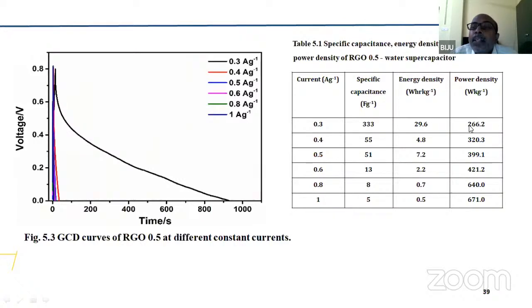The energy density and power density values were also estimated, and these values are not very high when you compare them with a supercapacitor that actually uses an electrolyte, because for applications, the previous speaker, Professor Libu, was presenting about micro supercapacitors where the power requirements were rather low. But if you want to use supercapacitors for some other applications, the capacitance expected is in very high current ranges. At those very high current ranges, our specific capacitance, energy density and power density are not that high. But when you come to the range of 0.3 ampere per gram or 0.4 ampere per gram, you have specific capacitance which is not negligible.